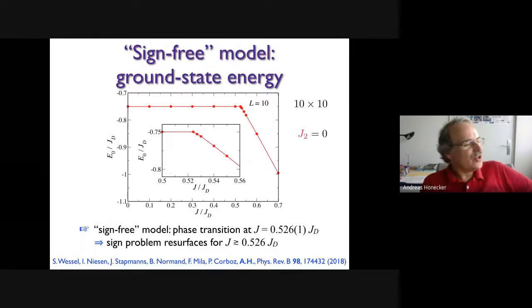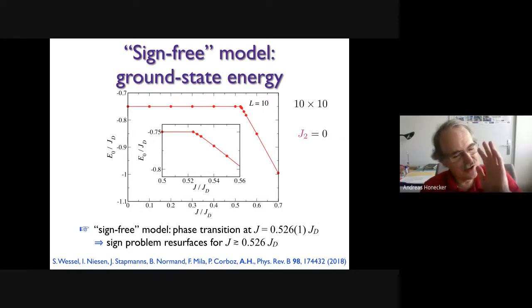Well, if you take the absolute value of the sign, you actually change the model. And that model has a phase transition. This, what we call the sign-free model, has a phase transition at an exchange ratio that is smaller than the phase transition in the real Shastry-Sutherland model. You also have, at weak interdimer coupling, the same exact dimer ground state, which is good, and that is the reason why it works. But then there is a phase transition in this sign-free model that precedes the phase transition in the true model. So if you wish, there's an algorithmic phase transition, and you can work until you get there. After that, it becomes again more difficult.